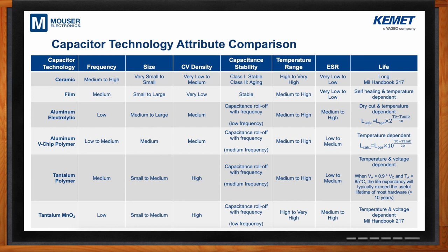So in the aluminum polymer, we use a simplified equation. For every 20 degrees C drop in temperature from the rated temperature, you're going to see a 10x increase in life. So if you're 2,000 hours at 125 degrees C, you go to 105 degrees C, now you've got a 20,000 hour operational life before your cap or ESR goes out of the limit for life calculation. And in the case of tantalum polymers, it's a little bit more nebulous, but generally, if you're 85 degrees C or lower and you're 9/10 of rated voltage or lower, you're going to see a usable life of 10 years or longer. And again, it depends on the actual condition that the parts are used in and the part number.